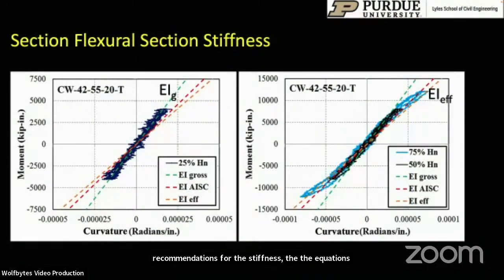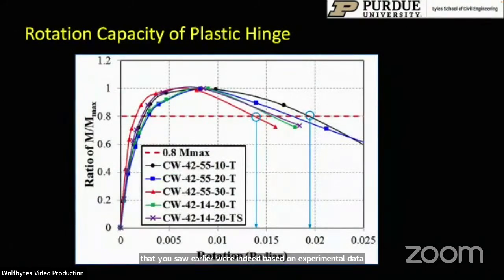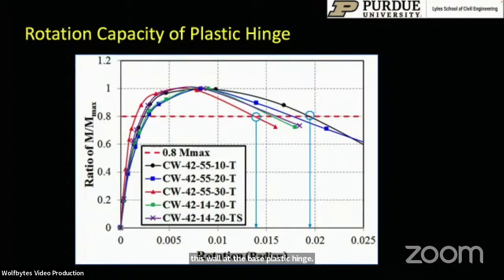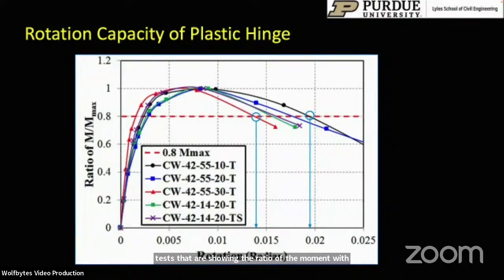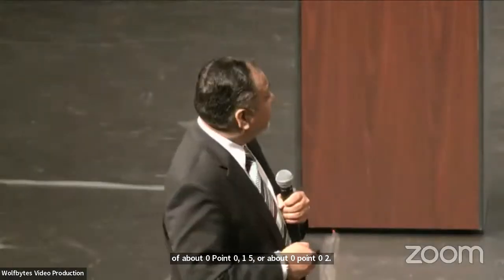And we were able to verify that those recommendations for the stiffness, the equations that you saw earlier, were indeed based on experimental data. From all of this experimental research, we were also able to look at the rotation capacity or the ductility of this wall at the base plastic hinge. I'm showing you here results from about 5 different tests that are showing the ratio of the moment with respect to the plastic rotation capacity of the hinge at the base, showing rotation capacities that were in the neighborhood of about 0.015 or about 0.02. And as the axial load increases, the rotation capacity decreases ever so slightly.